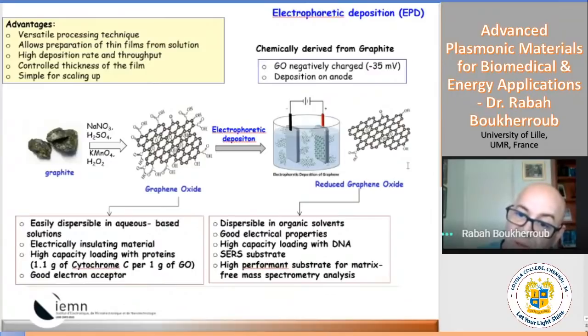Then what's happening is that these colloids or molecules or materials in this medium, if they are positively charged, go to the negatively charged electrode. The opposite way, if they are negatively charged, they will migrate to the positively charged electrode. So we can really very easily, simply and quickly modify any electrode material. However, the difference from the former one is that here I have to work with a conducting electrode, because I have to apply a voltage. Otherwise, I cannot do it on glass or other types, compared to the transfer of CVD graphene.